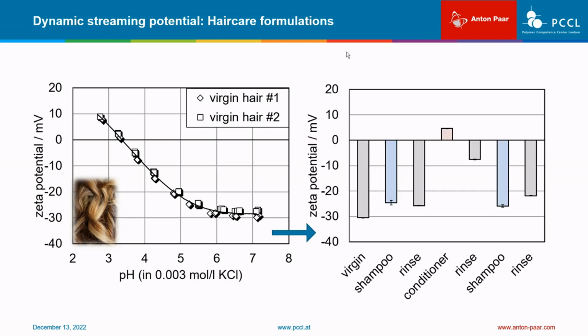In the next step, we use single point measurements of the Zeta potential, commonly determined in triplicate, to assess the affinity of hair care formulations such as shampoo and conditioner towards the hair fiber. Starting with Zeta potential for virgin hair at neutral pH of the aqueous buffer solutions, we apply shampoo and observe an increase indicating the effect of adsorption of an anionic surfactant. Rinsing again with the buffer solution returns the Zeta potential to the reference value of the virgin hair, but not completely. Apparently, there remains a permanent effect of shampoo treatment of the virgin hair.